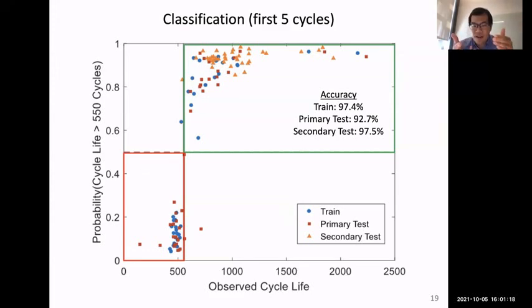We're able to take the first 5 cycles and immediately predict whether it's going to be above 550 or below 550. And this work, I think, is quite seminal in nature because prior to our work, it wasn't really thought as possible to accelerate the testing of battery, whether it's classification or prediction, by this amount, which is basically an amount equal to 10 to 100x of time saving.